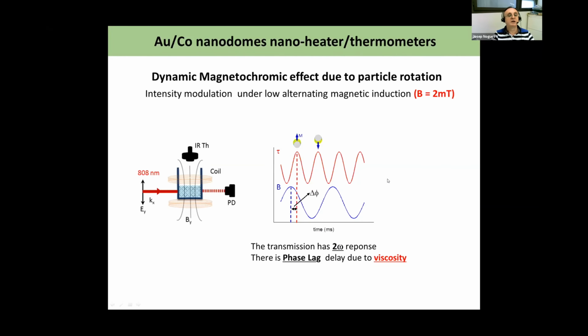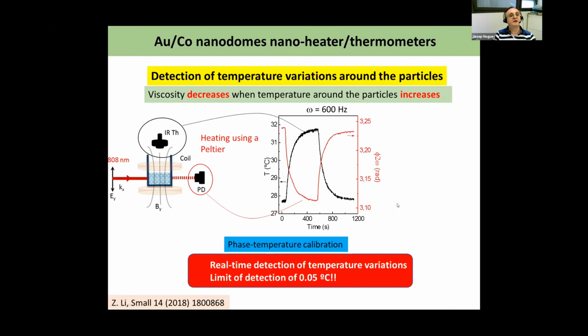And also there is a very important effect shown here by this line, that there is a phase lag between the applied field and the transmission response. And this is due to the viscosity of the liquid, meaning that the more viscous the liquid, the more difficult it is for the nanoparticles to rotate. So since the viscosity of a liquid depends strongly on the temperature, we will use this effect to measure the temperature surrounding the nanoparticles.